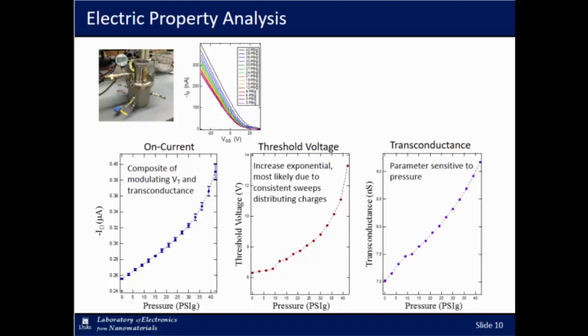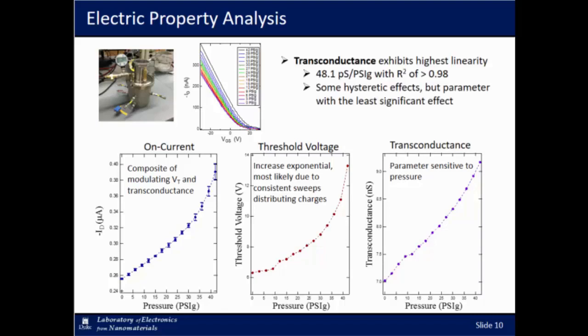So the parameter that we did see is sensitive to pressure is the transconductance, and this is fairly linear over this range. And what we see is a change of 48.1 picosiemens per psi, and an R squared value of 0.98 for the linearity. There's some hysteretic effects with this parameter. We're still working on this. I don't have those results here, but it's the parameter with the least amount of hysteretic effects. And we find that it decreases as you cycle it through pressure cycles.